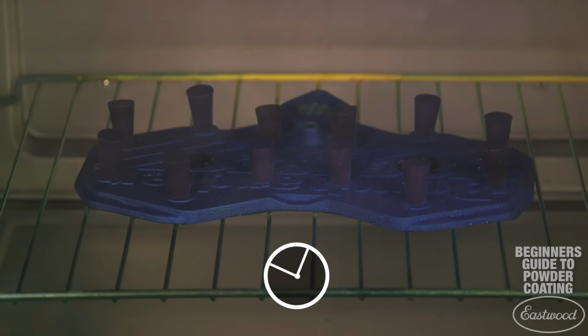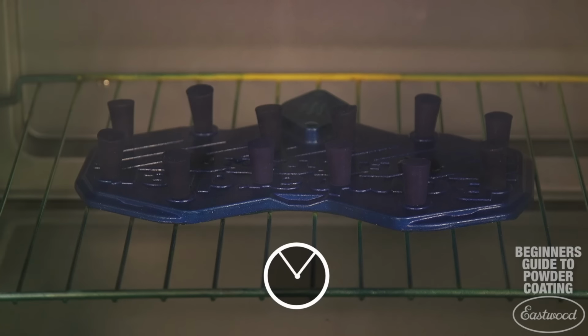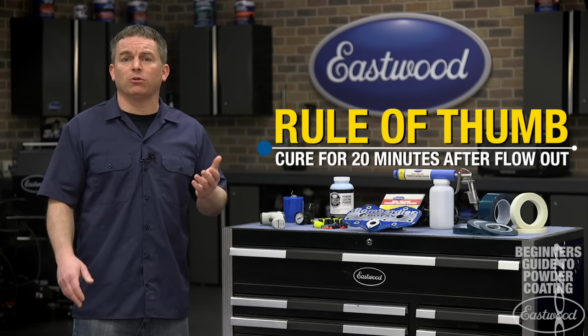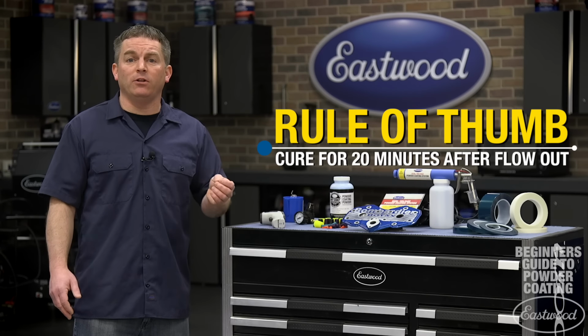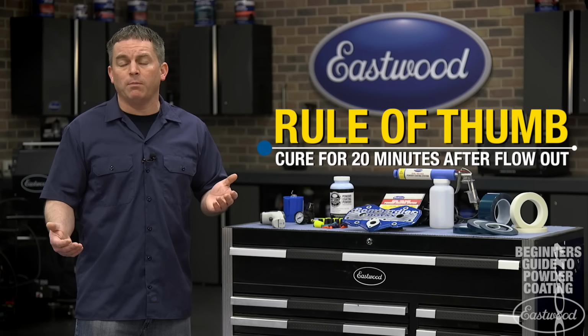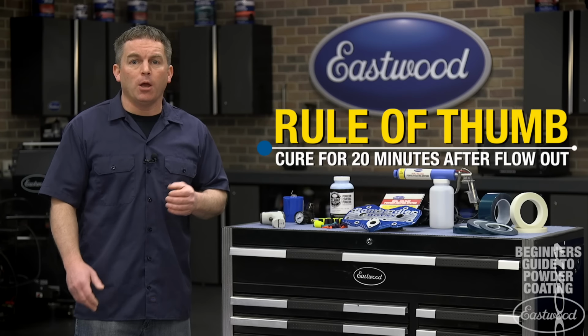You'll be able to see this happen as the powder becomes a smooth, even surface. If it's a gloss, it will start to shine at this point. A good rule of thumb is to allow the powder to flow out and then continue to cure it in the oven for an additional 20 minutes at 400 degrees Fahrenheit. But remember to check the instructions for the powder you're using.